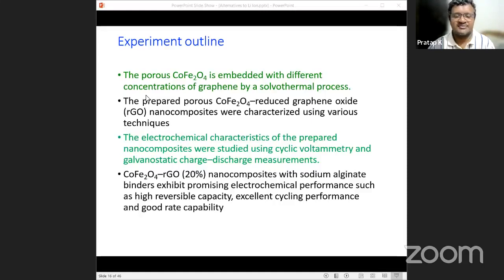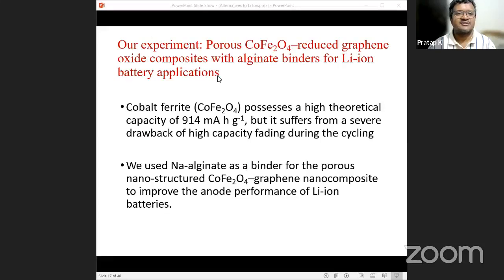We have added 20% of graphene into it. That is the third sample. We have added 30% of graphene into it. That is the fourth sample. We have added 40% of graphene into it. That is the fifth sample. So we have prepared cobalt ferrites with different graphene compositions. We did electrochemical characterizations, and what we found out is cobalt ferrite with 20% of reduced graphene oxide with sodium alginate binders has exhibited very good electrochemical properties, high reversible capacities, and excellent cycle performance.